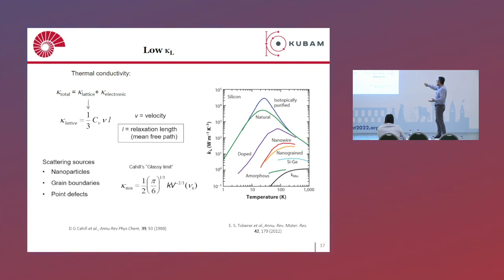In an alternative way, you can go from, let's say here, this is the lattice thermal conductivity of silicon with respect to the temperature. The natural silicon still has high thermal conductivity, but if you go lower the dimensionality, let's say from 3D to 2D or 1D, and then at the end, if you have the amorphous one, just make nanoparticles with an amorphous nature, then you can basically lower this lattice thermal conductivity to the glass regime.